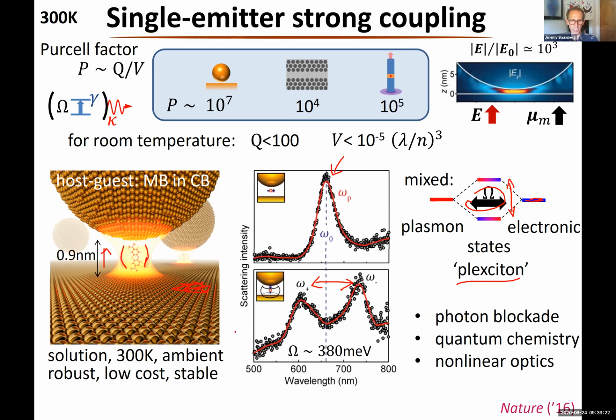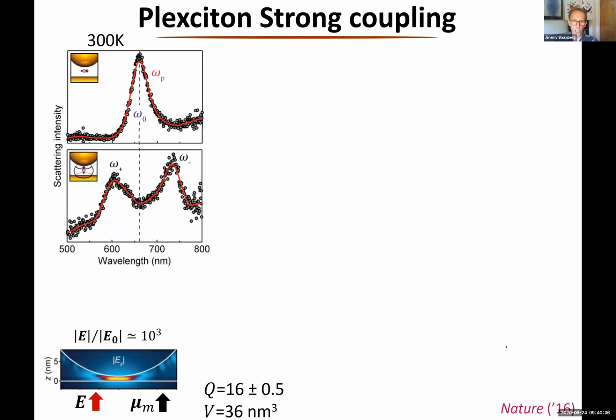So this is really nice because it's at room temperature. You've made them from solution. It's an ambient condition, so you can do chemistry. It's extremely robust. You make billions of them, and I didn't show you, but they're basically all the same everywhere over the sample. It's very low cost, and it's really stable, with some caveats that we should talk about. So this opens up a whole nice amount of experiments. For instance, we should be able to do photon blockade in the system, in other words, as soon as we put a photon into the system, it should behave differently. And indeed, we start to see that now. We should be able to do quantum chemistry, I'll talk about in a second, and all sorts of nonlinear optics. So quantum optics and quantum light emitters should be possible in this system. So that's what we actually did originally. I'll show you a little bit more of that as well.